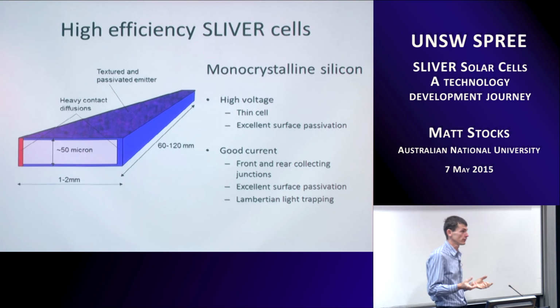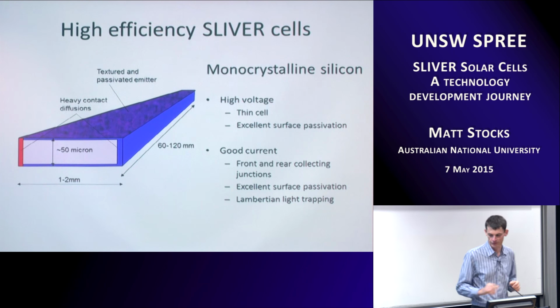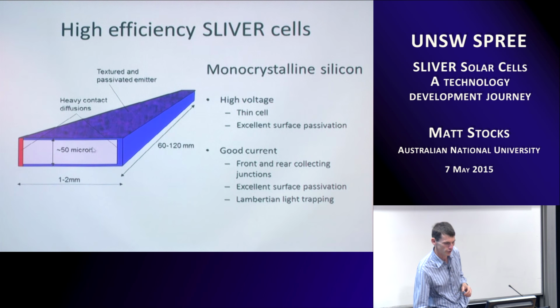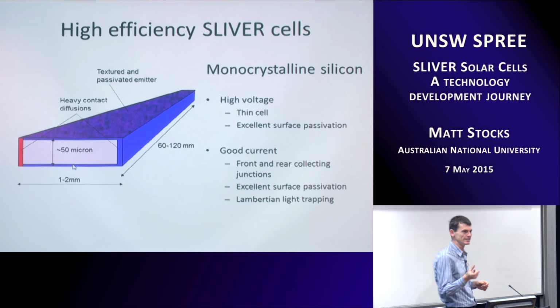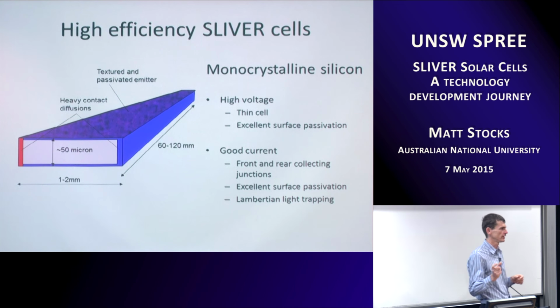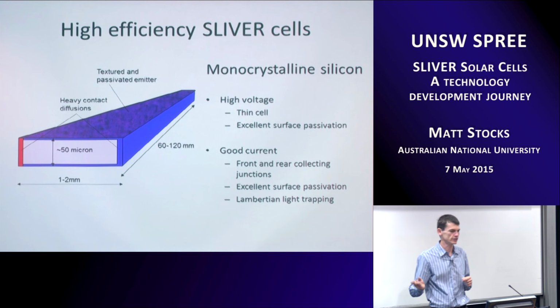Very good current. The cells are very, very thin, and we've got a collecting junction on both sides of the cells. So we have an emitter both on the top and on the bottom. So we only need 30, 40, 50 micron diffusion lengths to get the current from the centre of the cell out to our junction. So we get very good collection efficiency.